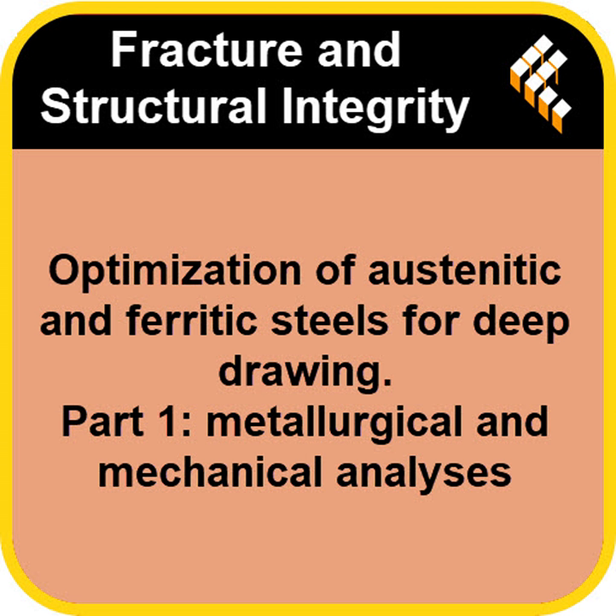So how big is this difference in stretchiness? Can we put numbers on it? Oh yeah, it's significant. If you look at the total elongation before fracture, the ferritic steels achieve only about 40% of what the austenitic steels can manage. Wow, so the austenitics are like 2.5 times stretchier. Roughly, yeah. And if you measure the total energy the material can absorb before it breaks, think of it as toughness and deformation. The ferritics manage only about 1/3 of the austenitic capacity.